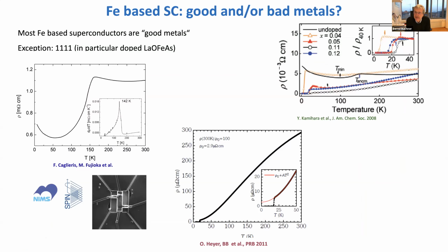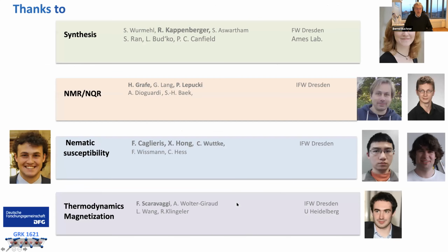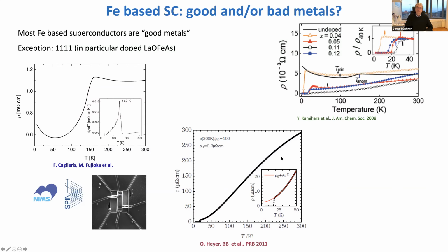Good or bad metals? Well, let's take this as a starting point. I think most of these iron-based superconductors, if you just look at the resistivity, behave like rather good metals. This is an example from our own work. This is lithium iron arsenide, which has a small residual resistance, more or less T squared at low temperatures, and a large resistance ratio. But there is one exception, and this exception is indeed these 1111 type superconductors, and this is the first report on superconductivity in these materials, and there you already see that you're basically dealing with something which is very close to localization, very close to insulating behavior.